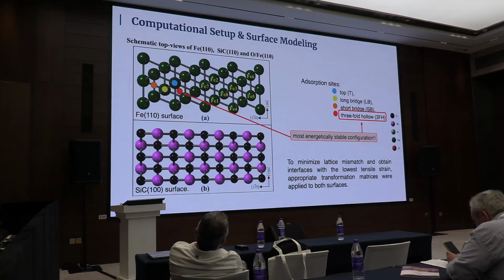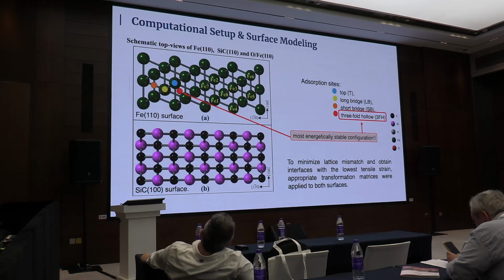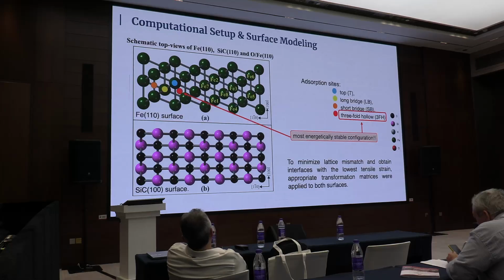So we start to make computations to know the best location for the adsorption of this oxygen. It's really known: the best adsorption site for this iron is there, and it is called threefold hollow. It's called hollow because it's located in a hollow between atoms, but it's threefold because it's not the pure hollow, which is this orange one, but if you see, it just shifts to the side there. So this is the most stable, and by most stable we mean lower energy. When a system is relaxed, the most favorable situation is the lower energy.